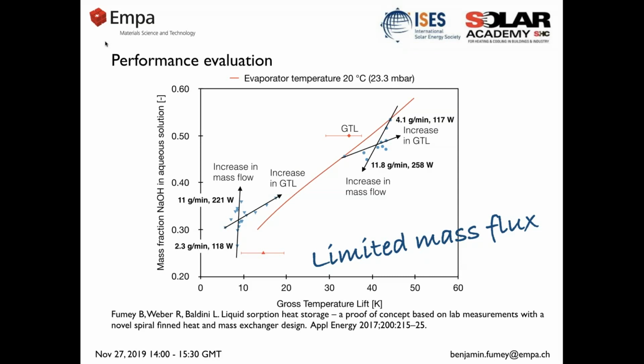But nevertheless, as an example here, we can show that depending, for example, on the mass flow, so how much sodium hydroxide, grams per minute, flows on the heat and mass exchanger, we see that we're closer or not so close to the equilibrium line. Here on the left bottom is a discharged state, and it is seen that even though mass flow is increased, the 11 grams per minute compared to the 2.3 grams per minute, the power is not substantially increased, but we divert away from the equilibrium line.